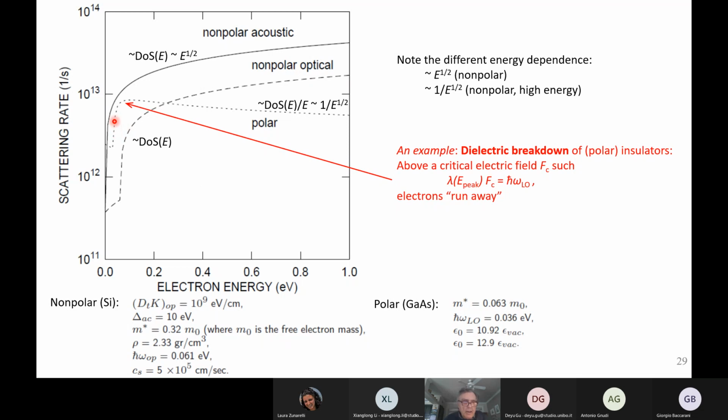So as they move along this line, towards the right, they go towards a higher scattering rate. That's good. If this were continuing forever, there would be no problem. But at this point, you reach a maximum. So if an electron now reaches an energy which is above, what is it, 150, 120 millielectron volts, something like that, above which the mean free path begins to increase, then the energy that you can gain between two collisions gets bigger than the energy that you can lose. So the electron will end up gaining even more energy from the field.